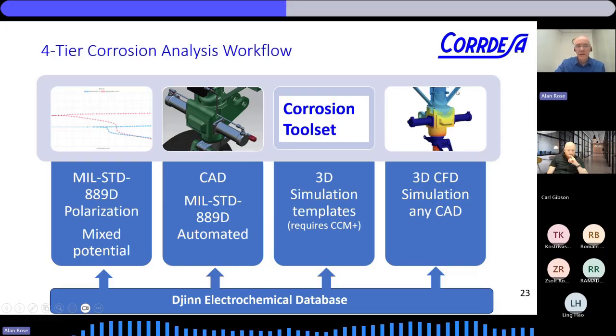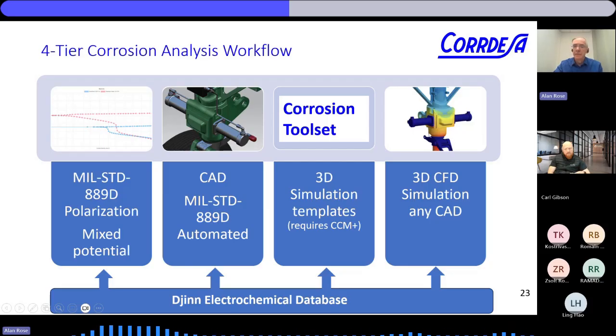So you can import the 3D CAD into your CFD solution, and we can solve for the corrosion rate. And you can get a corrosion rate map. So you can see the gradients as it changes from high to low corrosion rates over your assembly.